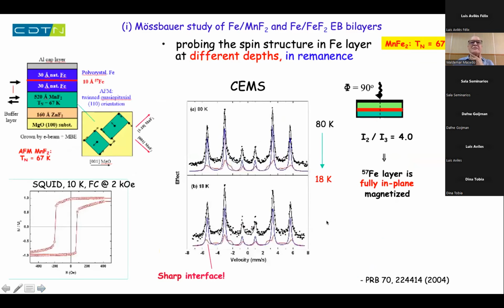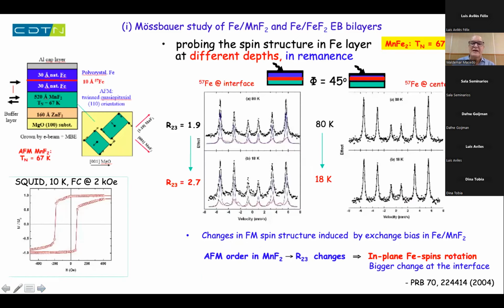For the exchange bias systems, one of the systems we have been studying years ago was the iron fluorides, and we basically prepared samples placing the iron 57 at different distances from the antiferromagnetic interface, and this shows that in these samples you have fully in-plane spins. That means if you want to see something, you have to go to non-perpendicular geometry, and this is what we did in this case. These measurements were done in remanence. What we have seen is that as long as you have the order of the antiferromagnetic layer, that means you go below the Néel temperature of the iron fluoride, you will see that the line intensities in these Mössbauer spectra change. That means we are proving that we have in-plane spin rotations in these samples, but it is in remanence.